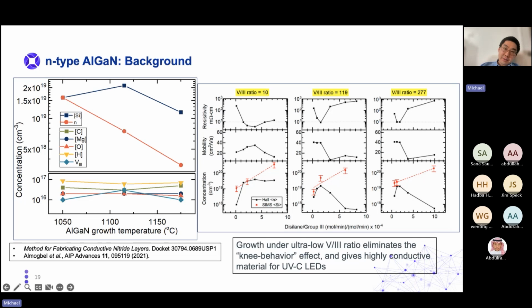So this V/III ratio, for those who don't know, is the ratio between the flow of group 5 element to the group 3 element. So group 5 is nitrogen, so ammonia, to group 3, which is trimethyl gallium and trimethyl aluminum. Another thing we discovered was that we were growing too hot in temperature, and lowering the temperature helps with the conductivity as well.